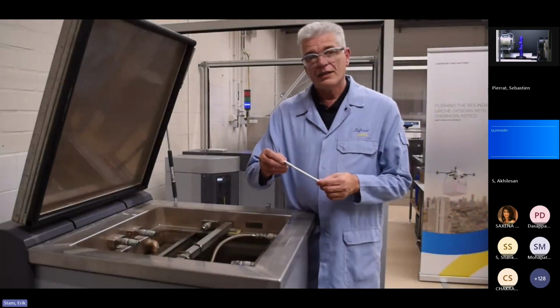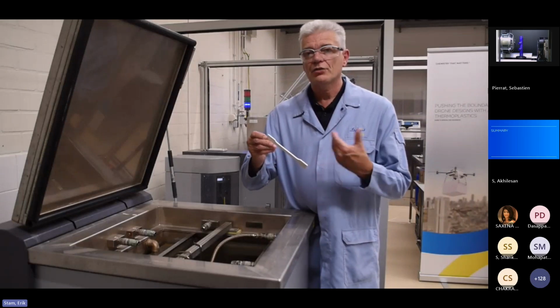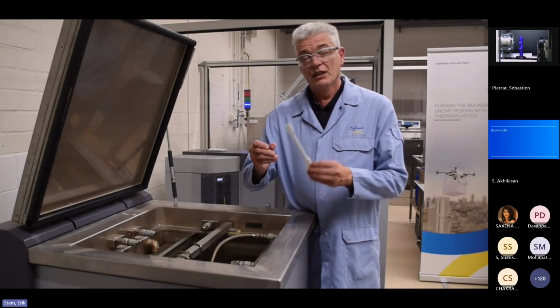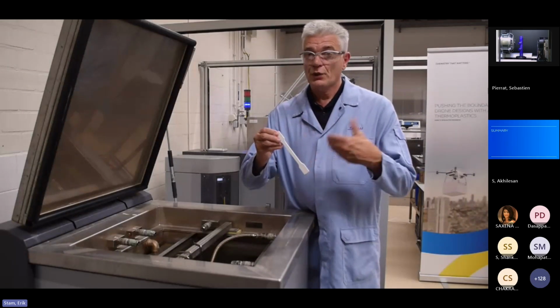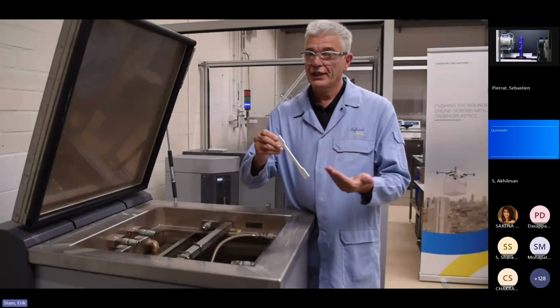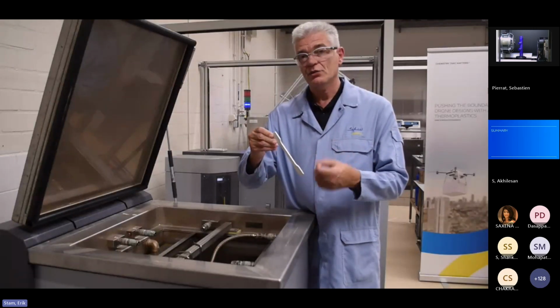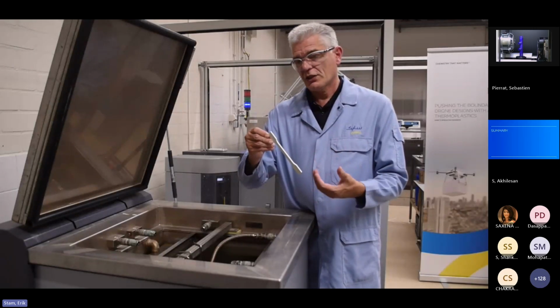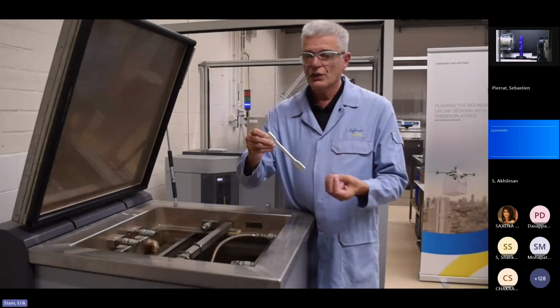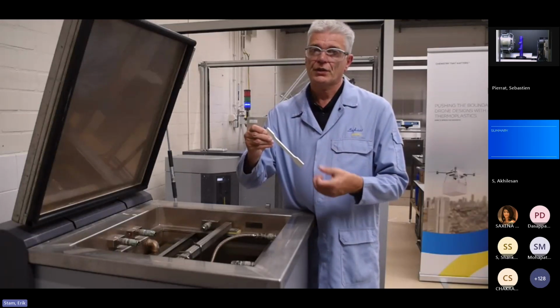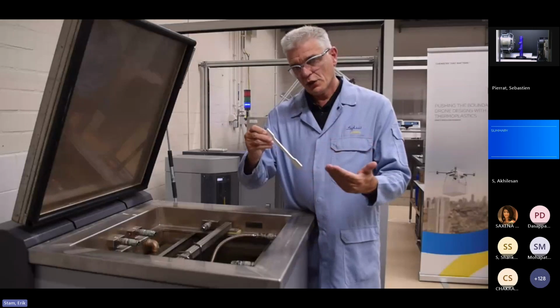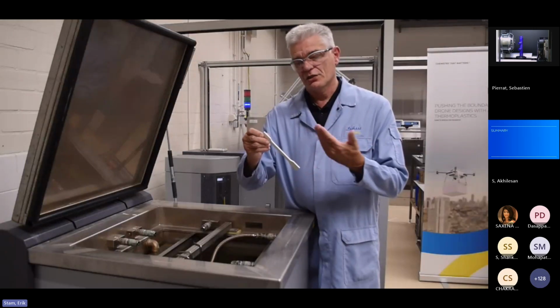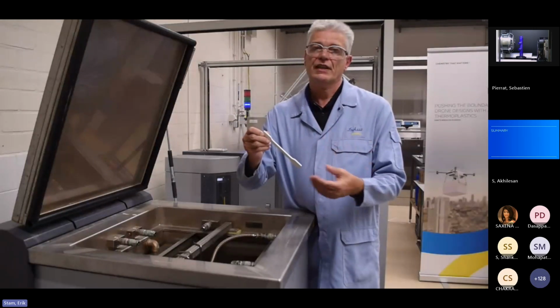The first thing we do is look at the hydrolytic stability of materials. For that, we use tensile bars. We expose them in hot water for 1 or 2 years, and then we determine whether the material can withstand the water. It sounds very simple, but I can tell you there are a lot of materials which cannot withstand hot water over a long period of time. And only those materials which are good candidates, so they can resist water for a long time,